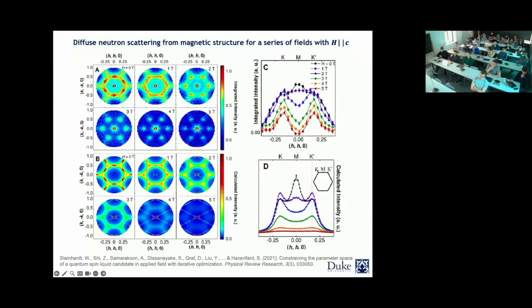Here I'm showing you the line cuts across the zone boundary, for example, at different fields. And you can see that the M point is being picked up at 0, and then it starts to go to the K points. And this is the simulation that they were able to get from these order parameter values. The whole point of this work was to say that even if you have site mixing in a compound, it's not a death sentence. And there may be some tuning parameters like the magnetic field or the pressure that would give us additional information so that we would be able to extract the order parameters a little bit better.